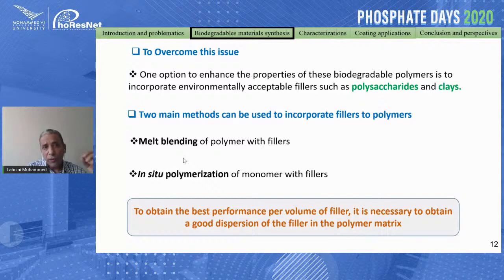The first method is really simple, but it is convenient when the fillers and the polymer have the same character, both hydrophobic or both hydrophilic. When one is hydrophilic and the other is hydrophobic, it is really difficult to have a good dispersion of the fillers in the polymer. It's like if you would like to mix oil with water. But in situ polymerization of monomer with fillers is a really good method, for example when we would like to polymerize the monomer by radical polymerization, because a filler with OH groups doesn't affect the radical polymerization.